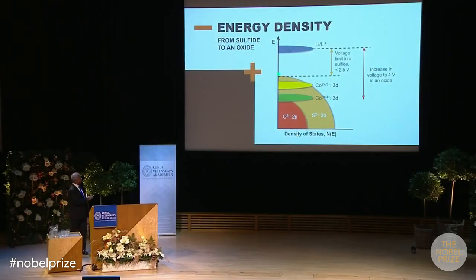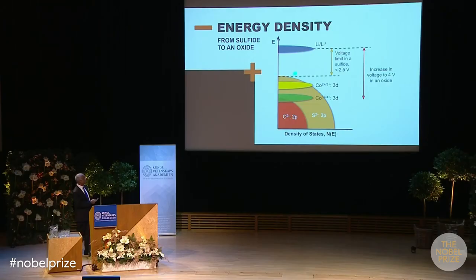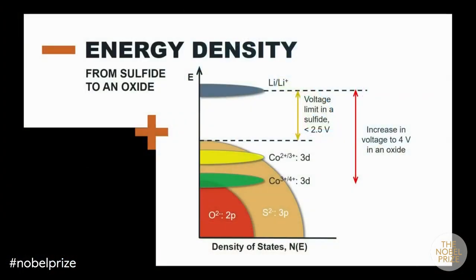So if you take the sulfur 3P band, it lies at a higher energy. So that means it's difficult to access these higher oxidation states, for example. Therefore, the voltage we get is limited by the top of the sulfur 3P because we cannot go below. On the other hand, the top of the oxygen 2P orbital lies at a higher energy. Therefore, we can easily access higher oxidation states like cobalt 3+ and cobalt 4+. So that can push the voltage from less than 2.5 to, for example, as high as 4 volt.